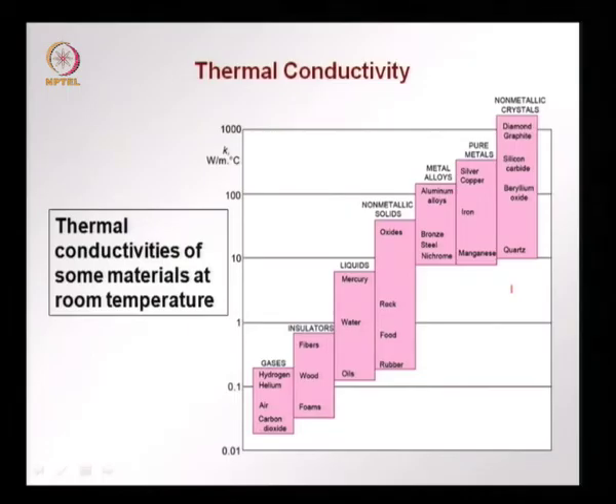There are a range of thermal conductivities for materials. So, this is at room temperature, and on the y axis we have the value of K, and you see a range of values. At the bottom are materials like gases, which are good insulators, and solids, which are good insulators, like fibrous materials which have a lot of air pockets and voids in them. Foams, polyurethane foam is a very good insulator that is often used in the filling of walls, so that heat does not go through. Then come the metals, then in other solids we have lower thermal conductivity in non-metallic solids, and in metals and very pure crystals we have higher thermal conductivity. These are good conductors, whereas these are good insulators.